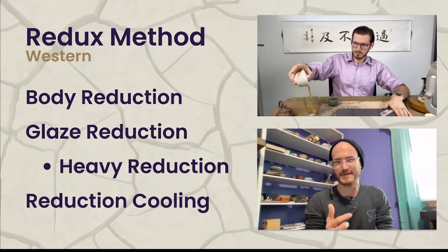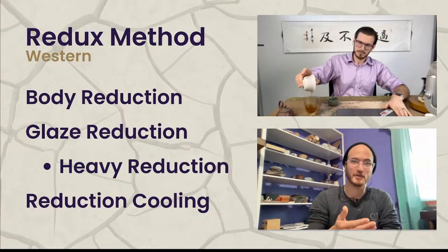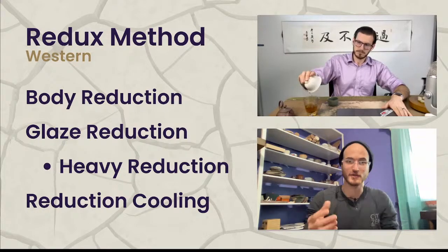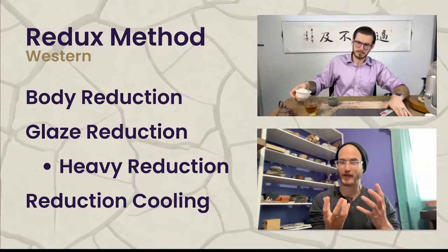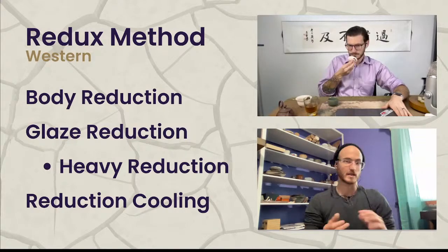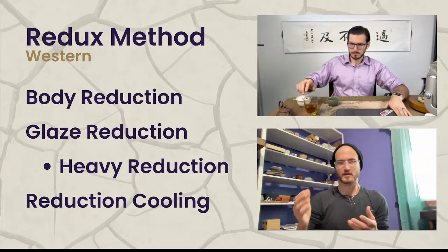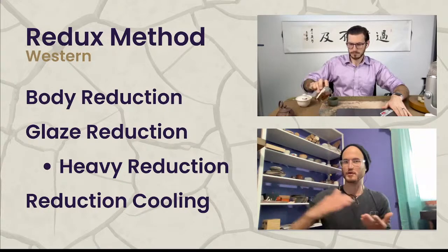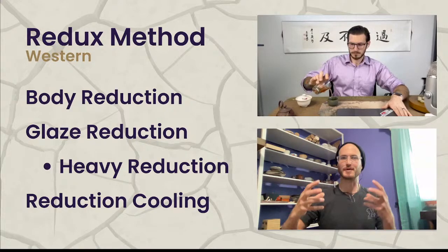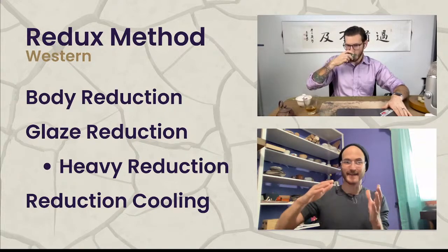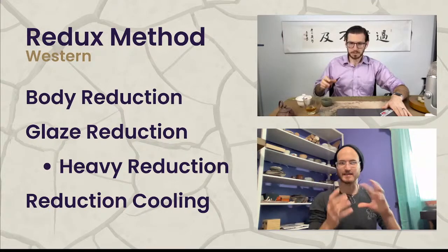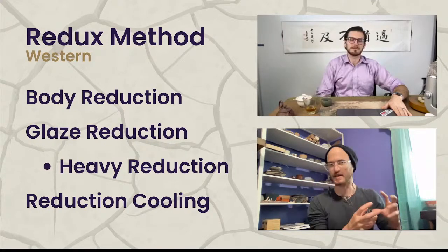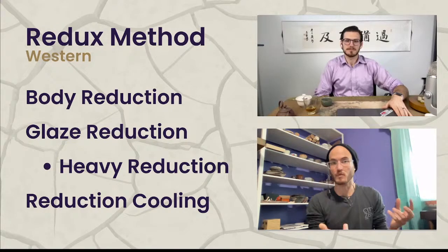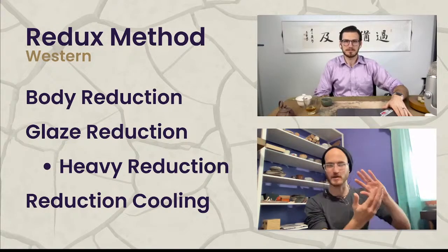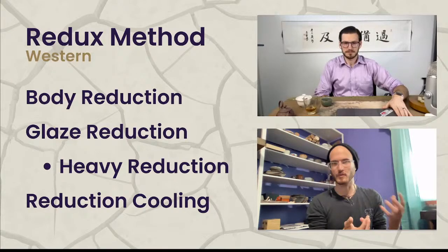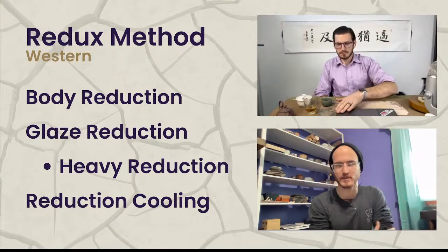And then the other thing is that you can have the problem with copper where you get re-oxidizing. So you've got this beautiful surface that you've developed in this glaze. And like you said, with the clay, you really don't have to worry about it. You've developed it over the firing and it's safe. With glaze, though, oftentimes if you've reduced a lot and you've done all this work to develop surfaces, and then you just stop and let it cool naturally, you can get some sort of backpedaling of the glaze where it changes color, which you could want if you want a varied surface where sometimes it's red, sometimes it's clear. Because copper never really will turn green in reduction. It really goes clear or red.